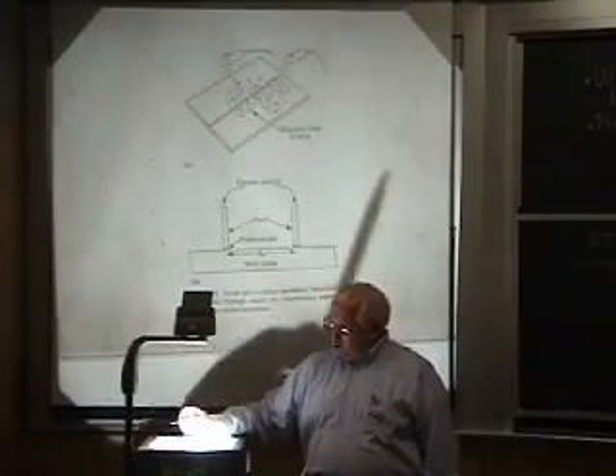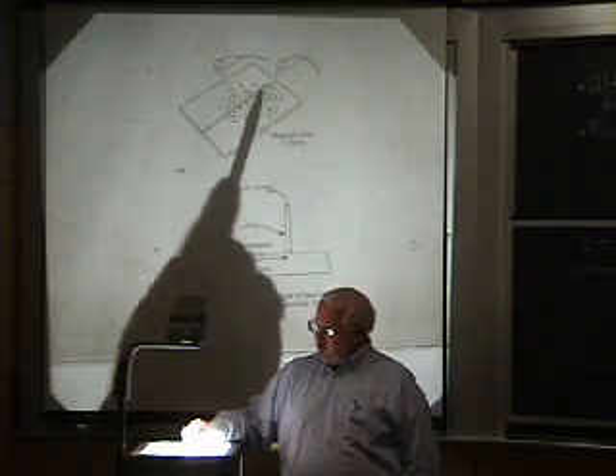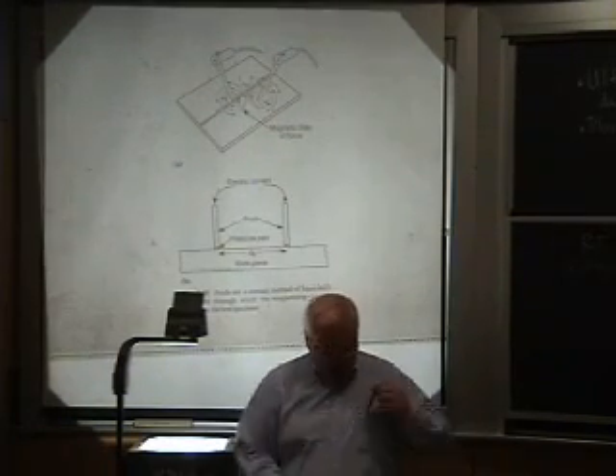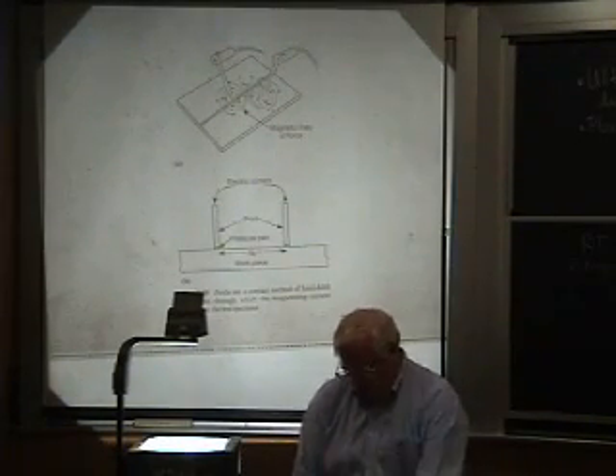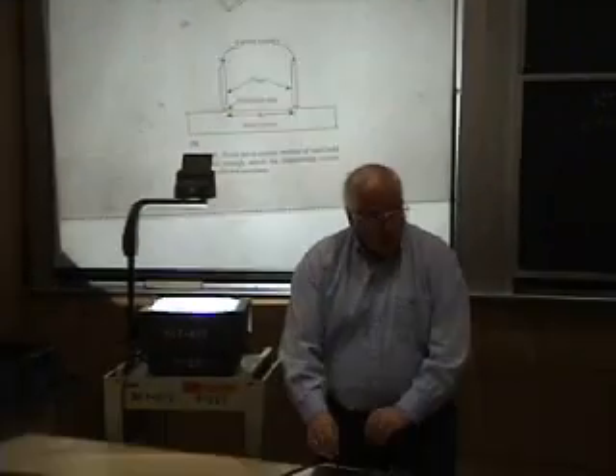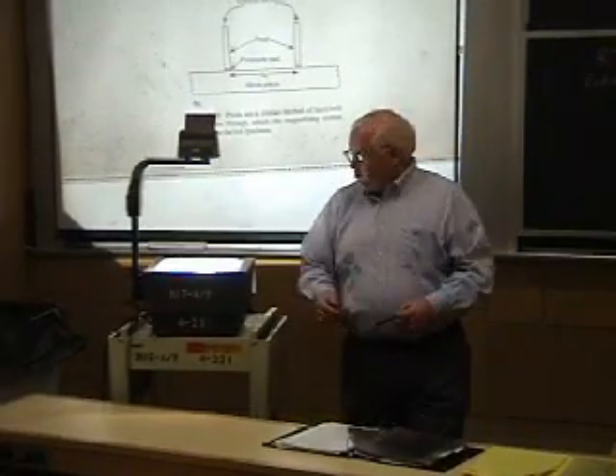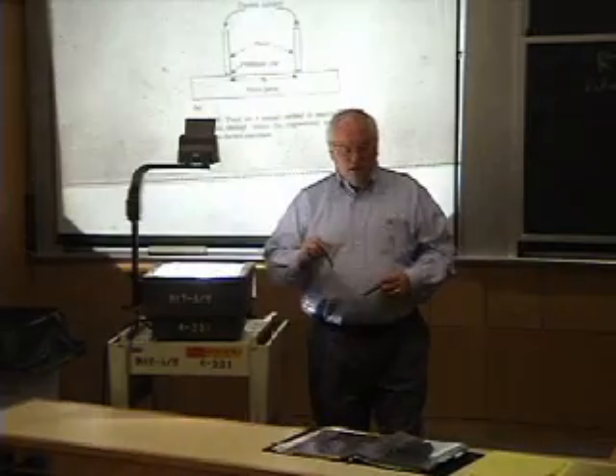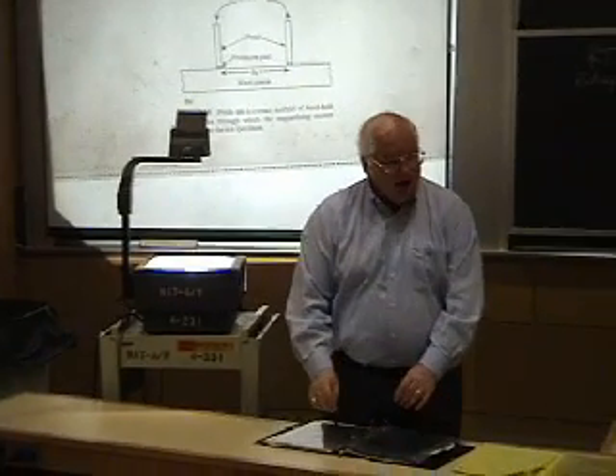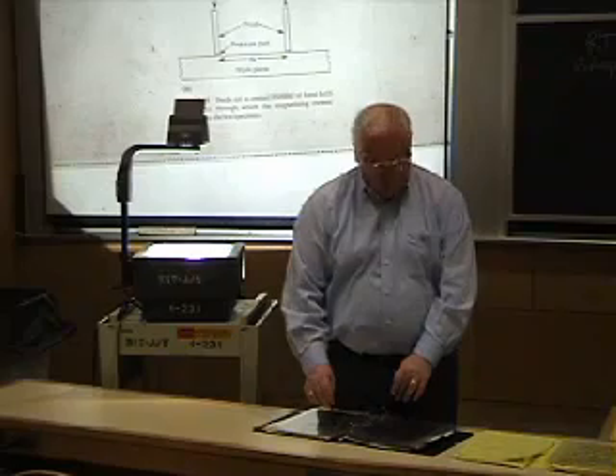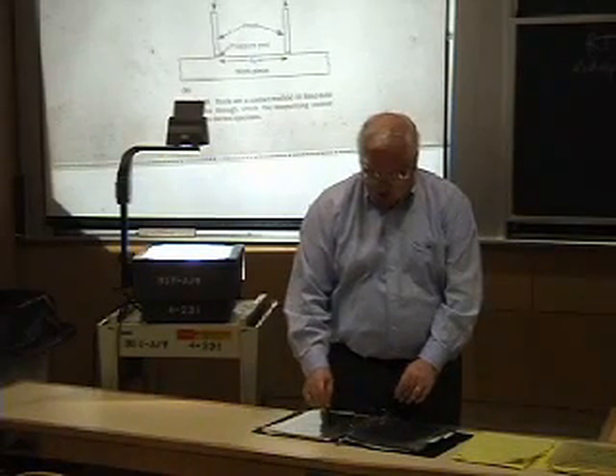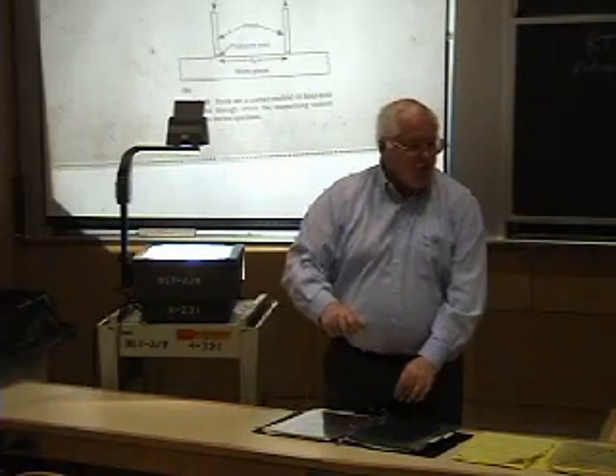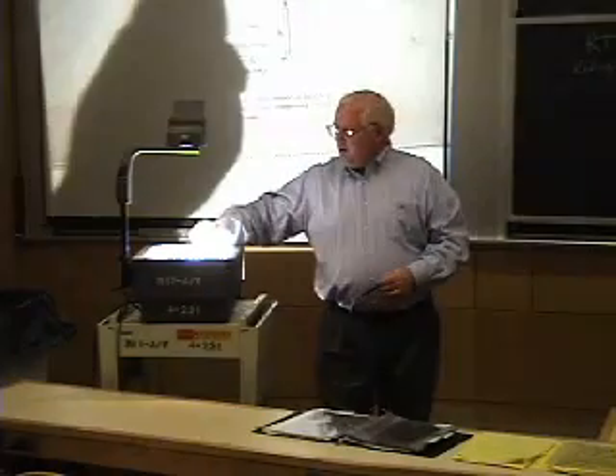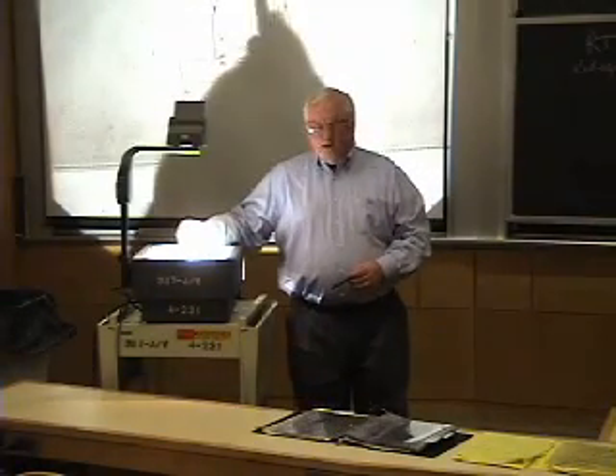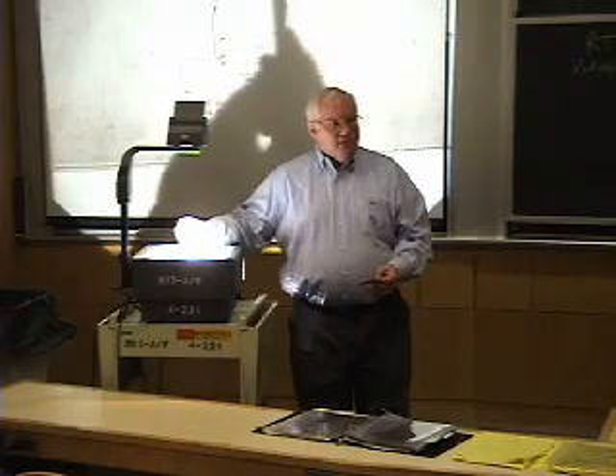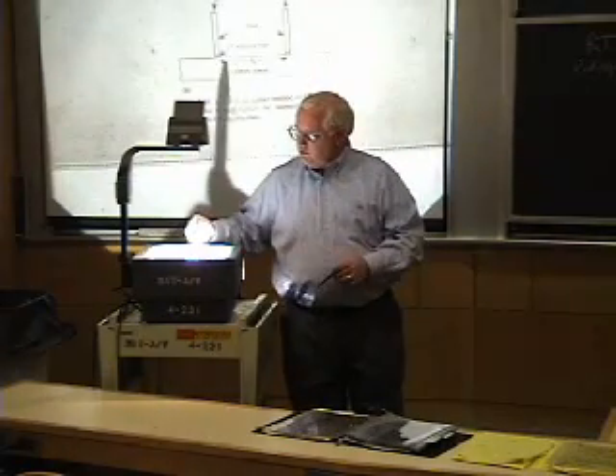If you put the proper amount of current through and you get this thing saturated, then you know what you're doing, and the operator has to change the locations of his prods. He might go like this, they might go like that, he might go over like this. The operators have been trained in order to get high magnetic fields, and you kind of need a third hand, and so sometimes you actually have 3 people or 2 people operating this. One person has to hold the prods on, the other person has to squirt the little dry powder on there in the area where you're looking for the crack. You've got to have the magnetic field oriented the right way in order to see the planar defect, and that's why they have to move these things around.